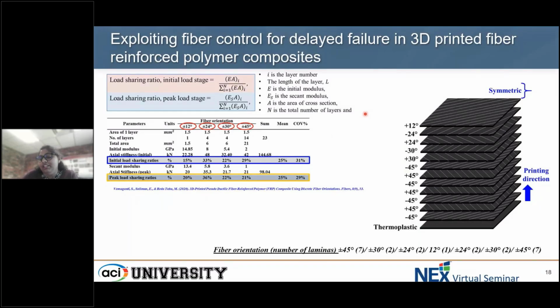So overall, when we started 3D printing this preliminary design, the first layer would be a thermoplastic floor, followed by the angles that are larger, and in a symmetric way. So if you had minus 45, that would balance out with a plus 45. And after the highest angle would be the lowest angle, and therefore the middlemost angle being the least amount, the smallest angle possible, and then these layers mirror them. So everything else on top is also symmetric.